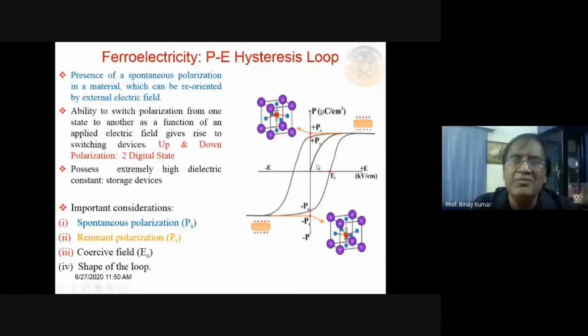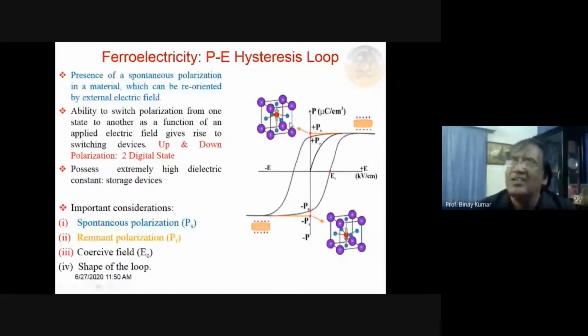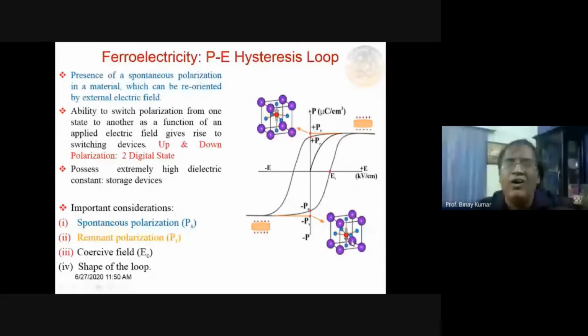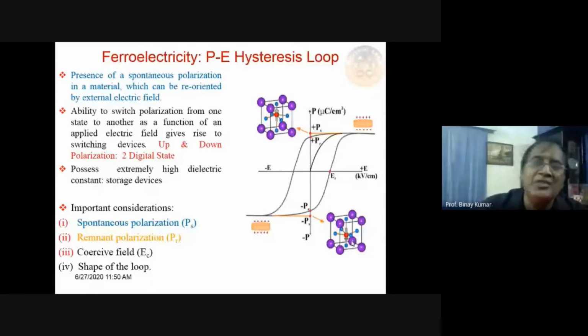You see that if I am in this state, this perovskite has a polarization vector which is upward. In this case, this vector is downward. What does it mean? In a PE loop, the ferroelectric loop, the material exists in two states: one is up polarization, one is down polarization. And for all digital applications, either a computer or many things, we require only two states, 0 state and 1 state. And the 0 and 1 state is here equivalent to two directions of polarization. So if polarization can be flipped up and down, it means the system can be used for all digital applications.